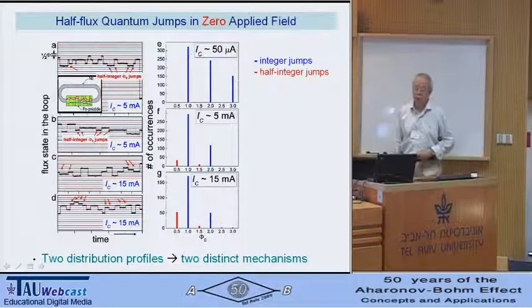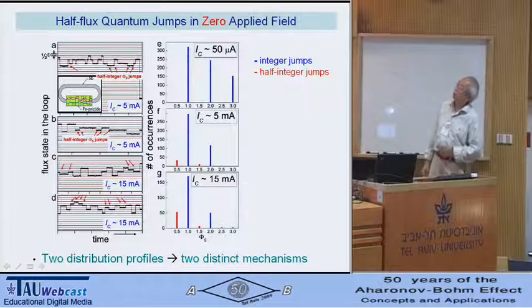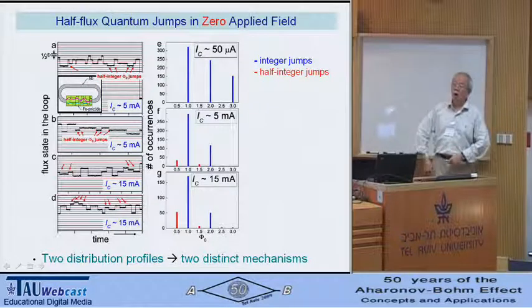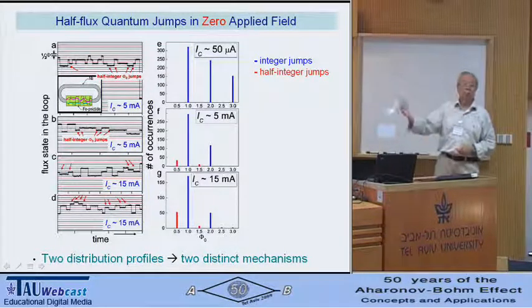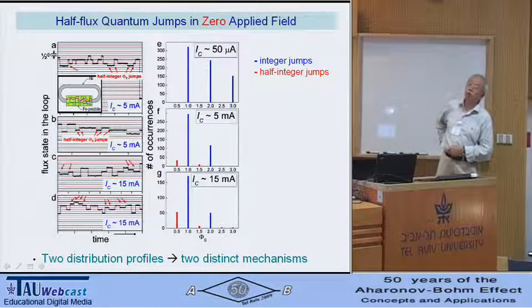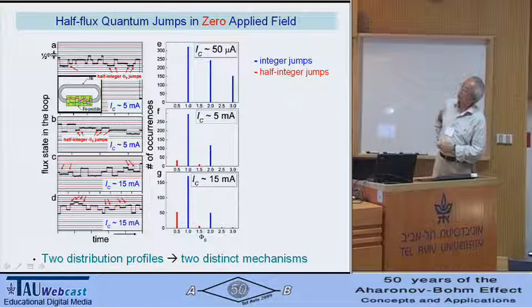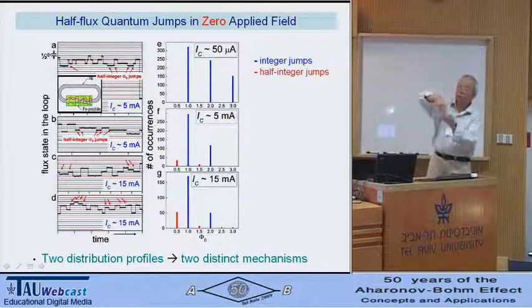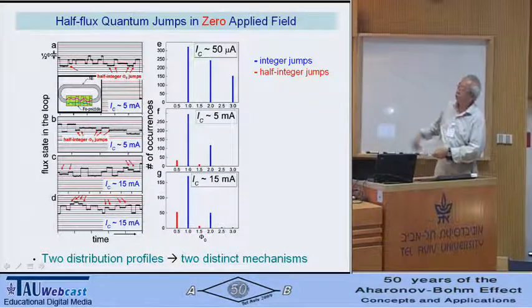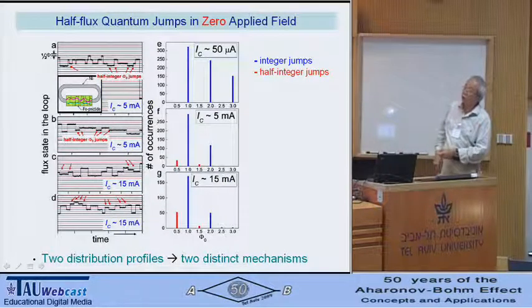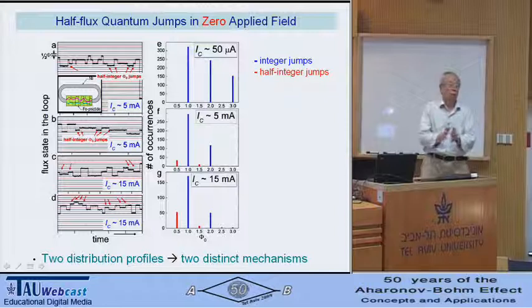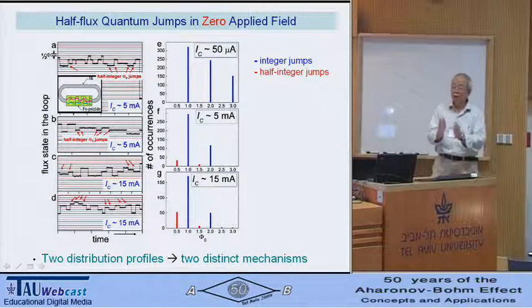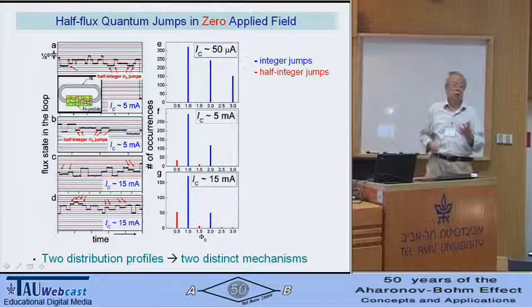Okay, here's a summary of the result as a function of coupling strengths. Since we observe hundreds of such flux quantum transitions, let's plot a histogram to see. Now, when the current is like this, you have only the integer flux jump. When you increase the current, you push the point contact a little bit harder, then you start to see the half flux quantum. Push more, you get more. But clearly, you see there are two distribution profiles. In other words, they're different. They're not just one story. There are two things. And that's consistent with what I just discussed.